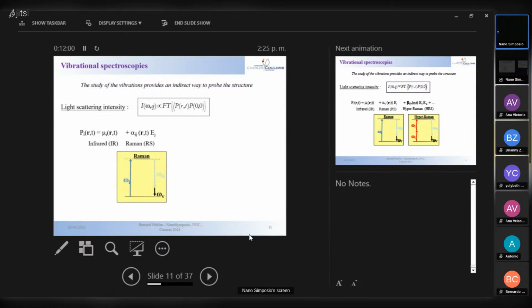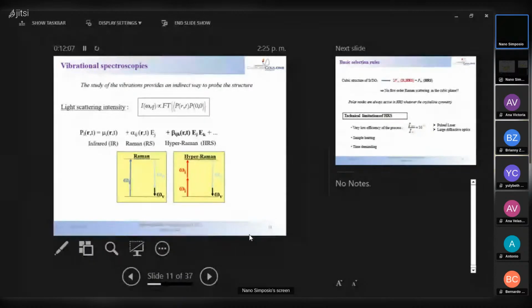And this vibration here will be our soft phonon mode. But if you continue this expansion here, at second order, you have what we call hyper-Raman scattering. Hyper-Raman is the first nonlinear term. So hyper-Raman is a nonlinear spectroscopy where you need two incident photons to scatter one photon after interaction with the vibration. And the interest of hyper-Raman is that it does not have the same selection rules as Raman. You see different modes than the modes you see in Raman.